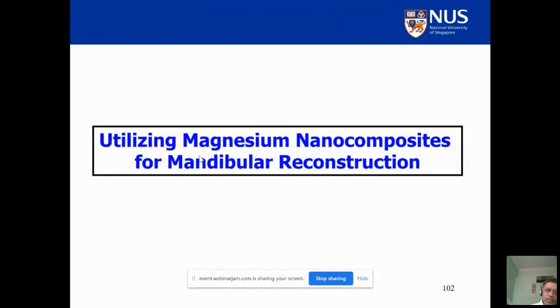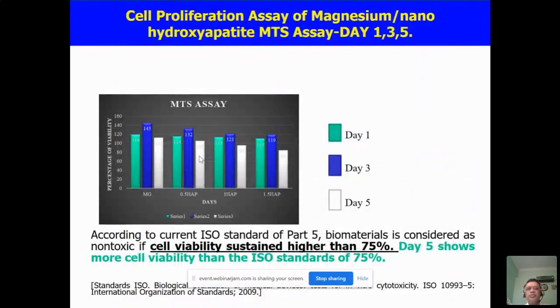We are also working with some dentists to see how it can be used in the repair of the jaw, mandibular usage. We gave them samples of magnesium with nano hydroxyapatite. They did the test, and from the test they say that the cell viability is more than 75%, which is a requirement to say that your material is non-toxic.